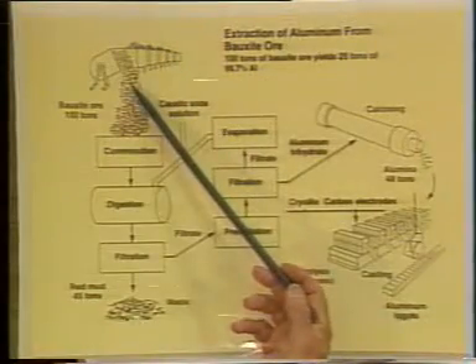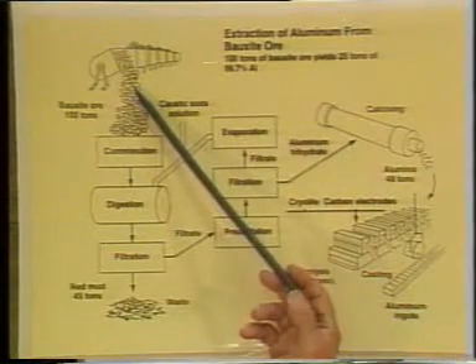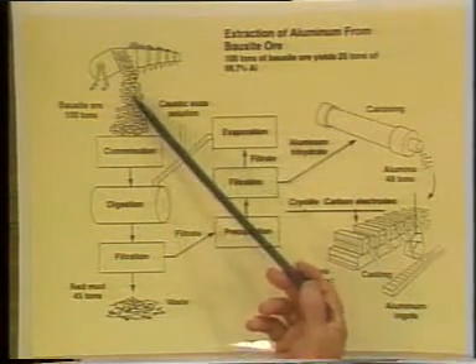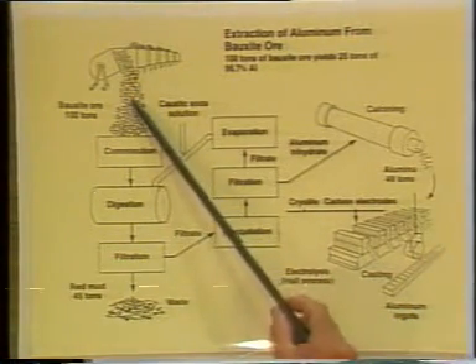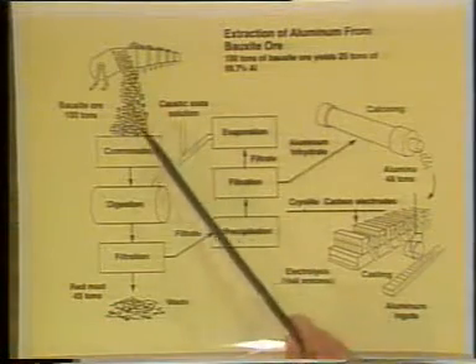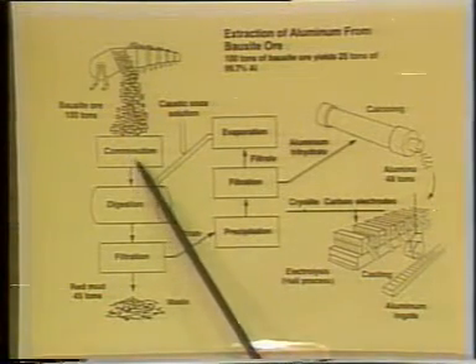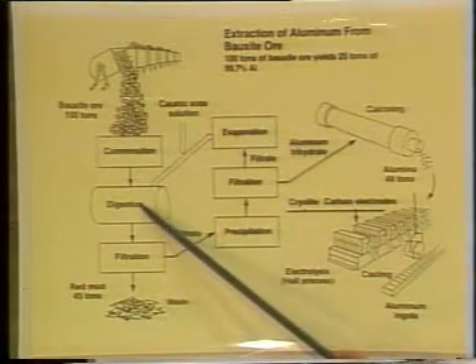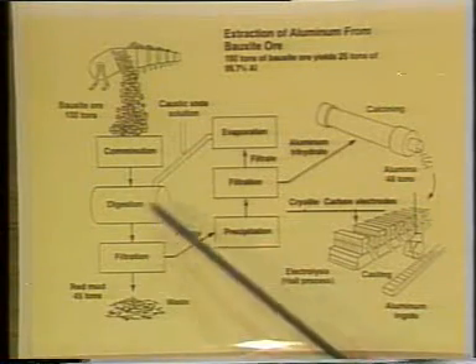And the process is called a Bayer process, spelled just like the aspirin, Bayer aspirin, except it's the Bayer process. And in the Bayer process, we take the bauxite ore, which is a combination of iron oxides, silicon oxides, and aluminum oxide. And we treat it, we grind it up first of all so we can dissolve it, and then we digest it or treat it with sodium hydroxide, caustic soda solution.